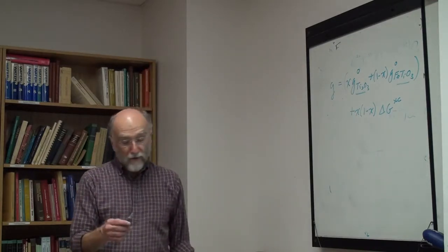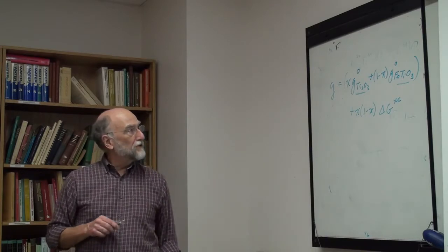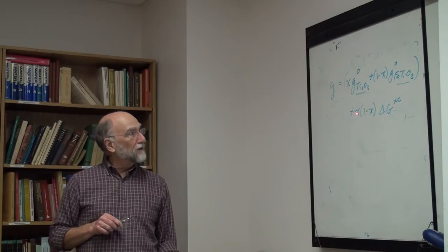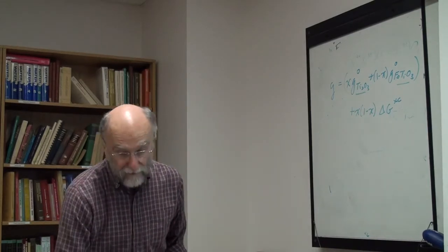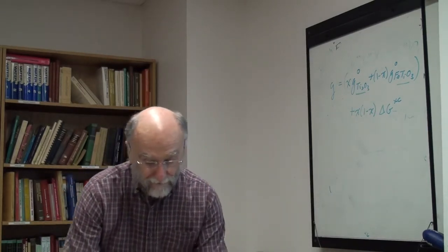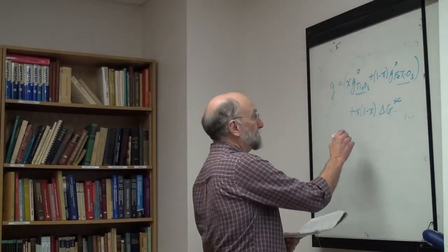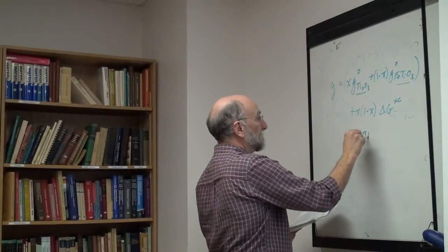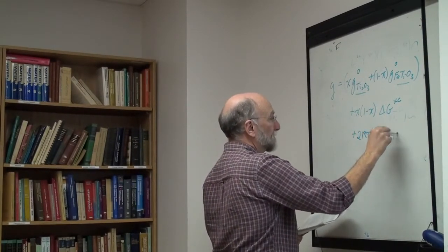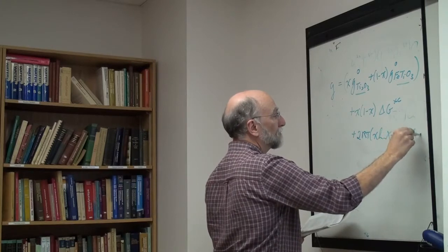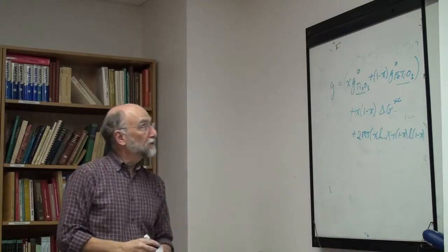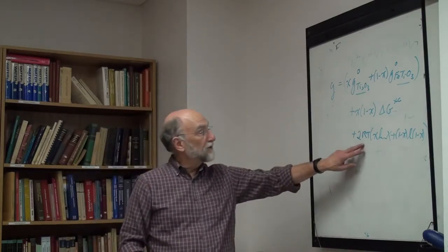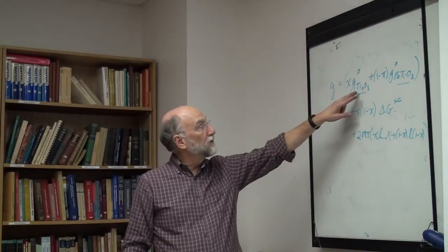So what have we come up with? We've come up with basically what's like a regular solution. It's a regular solution between Ti2O3 and FeTiO3. Sorry, we got to add on these. Plus the 2RT x log x plus mixing term as well. There's a mixing term for it. So this is your ideal mixing. So it's basically a regular solution, although you're mixing two sublattices.